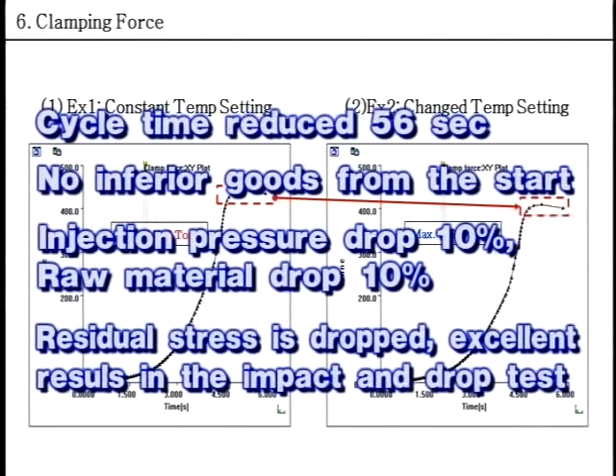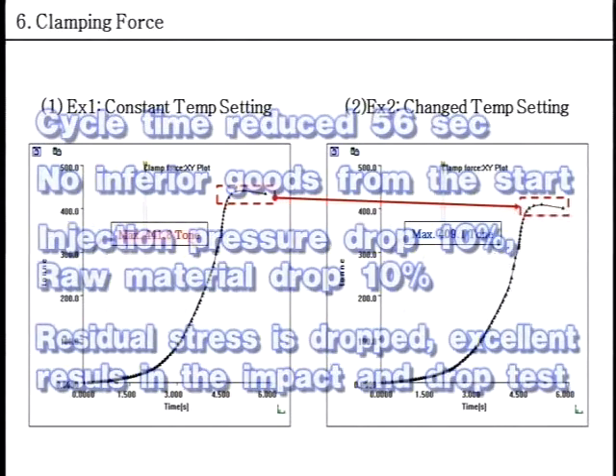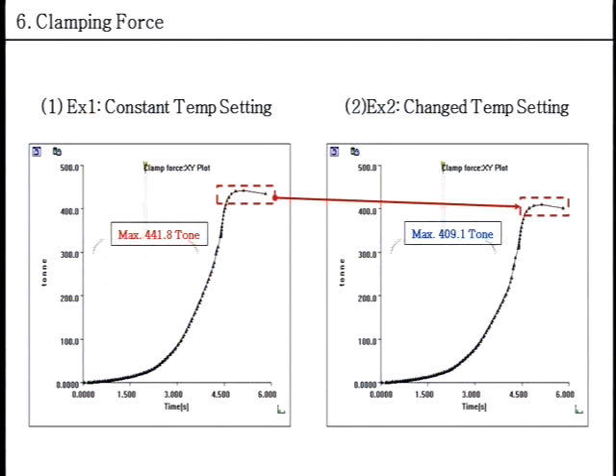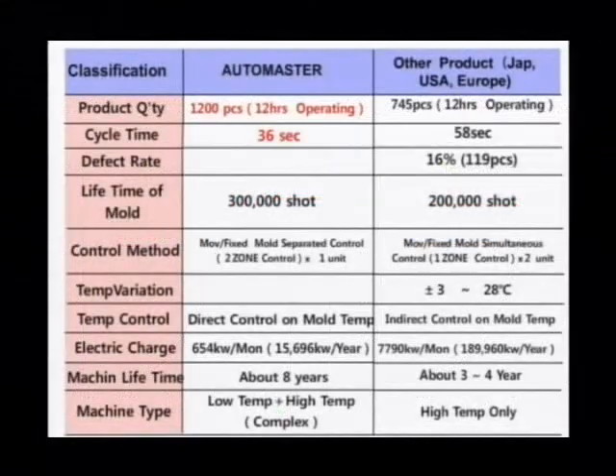Mold's clamping force is reduced, and the injection pressure is dropped, which help the quality of mold to be kept continuously, the defect rate of mold to be dropped, and mold's span of life to be lengthened. The weight of product becomes lighter, and the residual internal stress is dropped remarkably, so it attains excellent results in the impact and drop test.